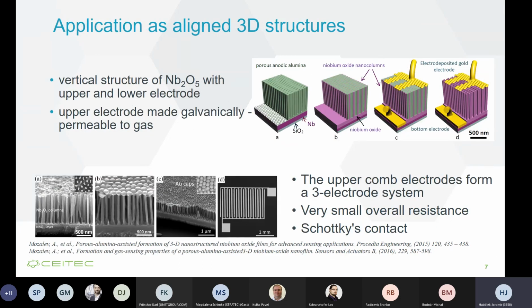Another approach using these techniques is to form 3D structures. It is a vertically aligned structure between upper and lower electrode. You can see in this picture the steps to fabricate it. The upper electrode is made by galvanic deposition to create this comb. This electrode is permeable to gas. The upper electrode can also be split into 2 electrodes, so we obtain a 3 electrode system: 2 electrodes on top and 1 electrode on the bottom.